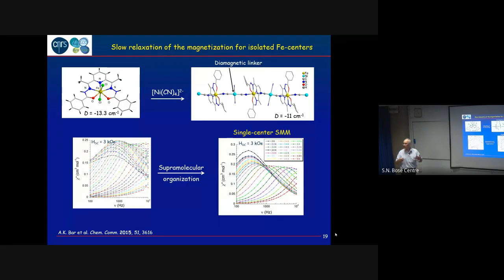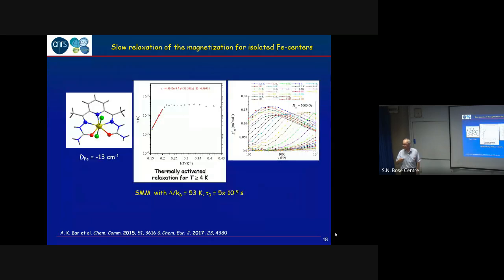What is limiting this to 3.15? Temperature, you cannot go beyond a certain temperature? We cannot go below 2. And also it's a matter of frequency. So it's high temperature. Yeah. Oh, because the signal is vanishing. So relaxation is so fast that we cannot manage it. And even here we have 10,000 hertz, but very, very fast.